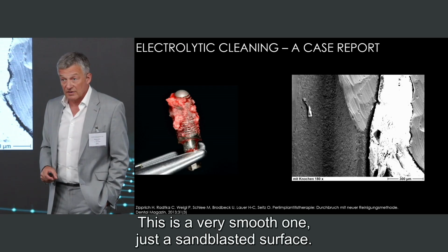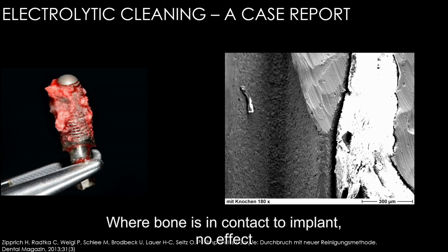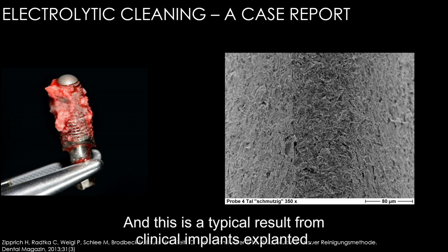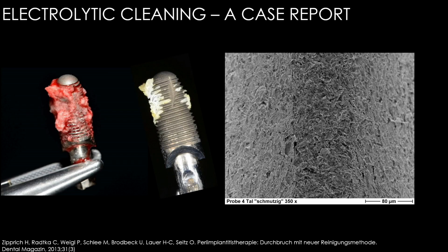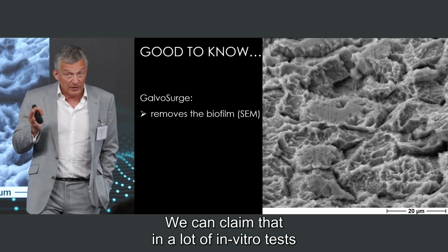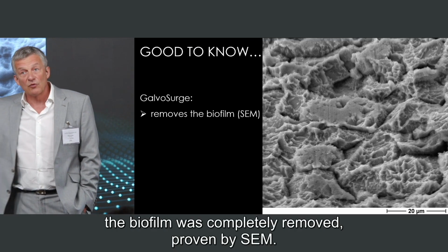I picked out 2. This is a very smooth one, just a sandblasted surface. This is bone. Where bone is in contact to the implant, no effect, because the electrolyte was not in contact. So that just cleans the exposed metal where the electrolyte is in contact. And this is the typical result from clinical implants, explanted, so not a single bacterium to be detected. And where bone was in contact to the screw, no effect. We can claim that in a lot of in vitro tests, the biofilm was completely removed, proven by SEM.